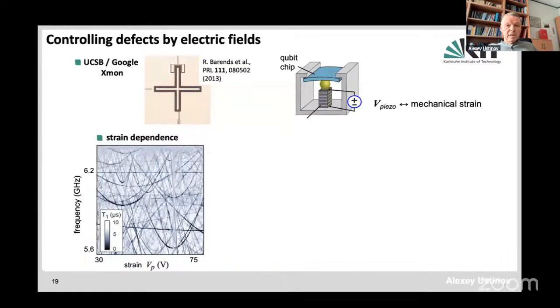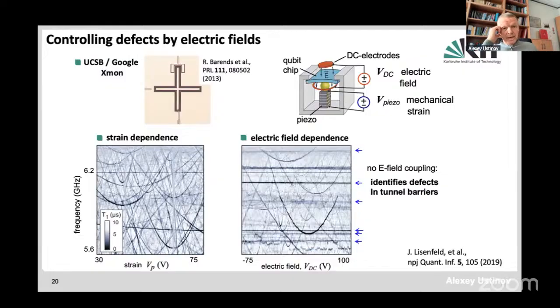Now, what is more recent, it's also already about 5-6 years that we are doing that. We are not only able to control these defects by strain, but we can also control them by electric field. So here you see the setting on the right, where we have the setup I already explained, the qubit chip clamped between two metallic supporting bars, and by applying a voltage to the piezo actuator, we could bend the chip. The result of these measurements is shown at the bottom left. Now, as shown on top right in this modified plot, we apply an external voltage, which could simply be a gate electrode located above the chip, on one side or the other side of the substrate. This electric field will influence defects on the surface.